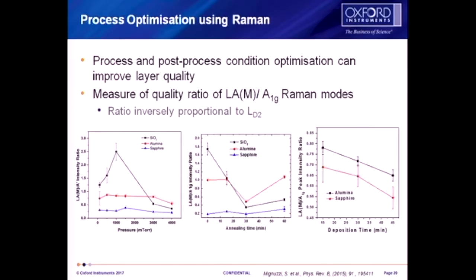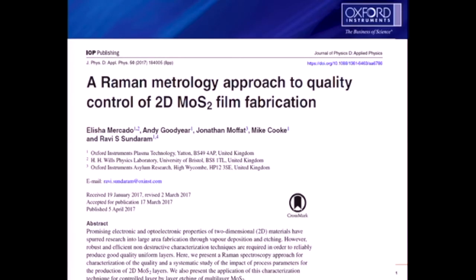And if you look down here, we can look at some process parameters we've looked at. You can see that the substrate has a big effect on it. Aluminum oxide and sapphire typically are not far off being the same material, but obviously more crystalline. But you can get very good material by playing around with the properties, and that's reported in this paper here. You don't have to write it down, but the slides will be available for you to read and get the notes off it.